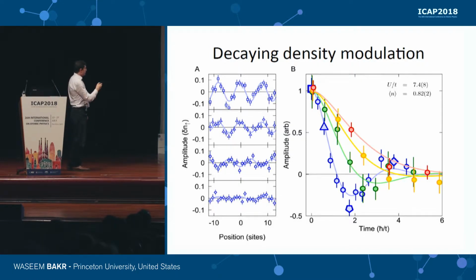OK, so that's the kind of data we take. And the curves that we're putting on top of this is a simple fit. So we're using just 2 fit parameters. These fits look like a damped harmonic oscillator. So we fit the frequency of the oscillator and the damping. OK, and for all the curves, the fit works with a single frequency and a single damping.